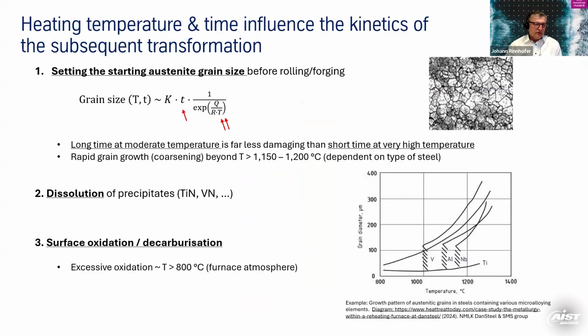So there we have two significant variables. This is the heating time and also the heating temperature. It is very important not to heat at too high temperatures, because you will get very, very coarse grains, which we don't want. So we want a very uniform and small grain-sized austenite structure before rolling.